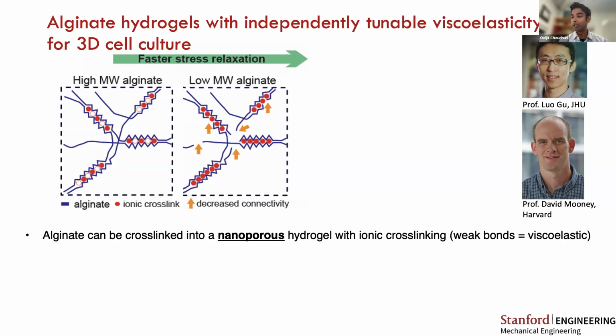So the materials approach we came up with was based on alginate hydrogels. So alginate is a polymer derived from algae. We can cross-link it into a nanoporous hydrogel using divalent cations such as calcium. Now, importantly, these are ionic cross-links. They're very weak. They can unbind and rebind quite easily, making these hydrogels intrinsically quite viscoelastic.